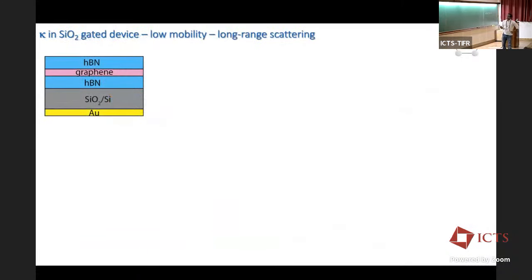And so why did we choose graphene? In graphene, I can have a system where I can put a metallic gate between the graphene and the source of long-range scattering to screen it. In graphene, the source of long-range scattering will be the dangling bonds from SiO2. So the first device which we make has hexagonal boron nitride encapsulated graphene directly on silicon dioxide.